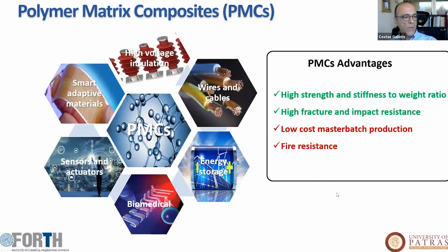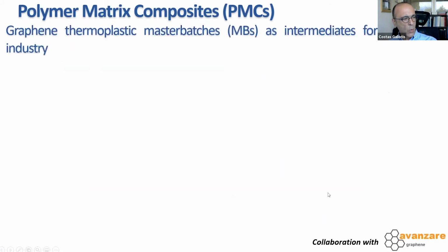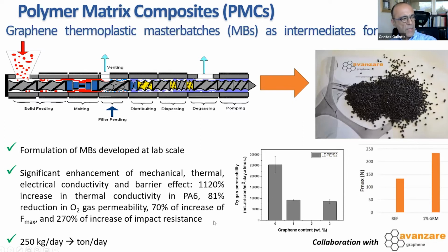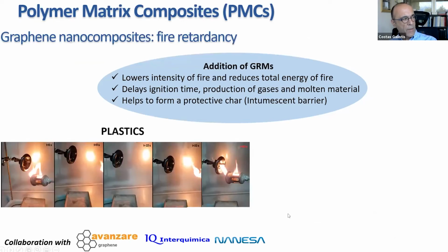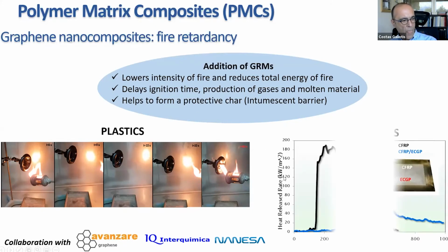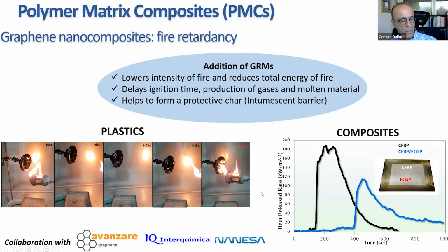So we have the polymer composites here. I'll show you the work we do, which is making master batches. This is a collaboration with another flagship partner. We're making master batches that incorporate polymer and graphene flakes, and it's easier to process. They enhance nylon with thermal conductivity, increased impact resistance, barrier properties, and more importantly, fire resistance, fire retardancy, where you try to burn a polymeric handle. As you will see here, it doesn't burn. It forms a protective char, and this is a composite with and without graphene in the matrix. You will see how it behaves, and it doesn't burn fully.